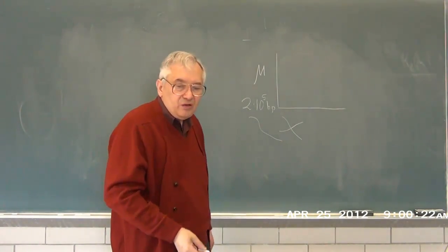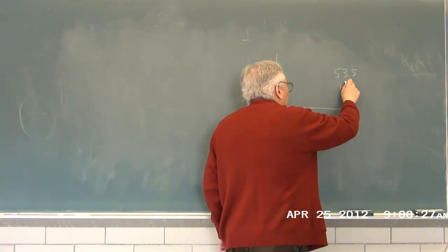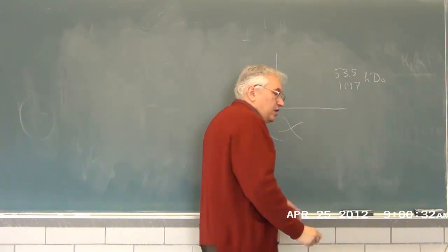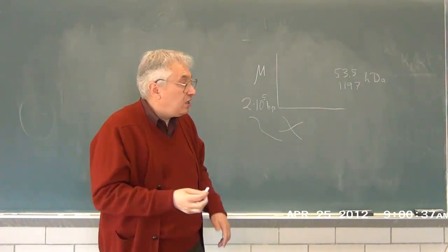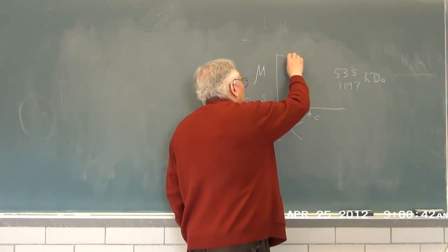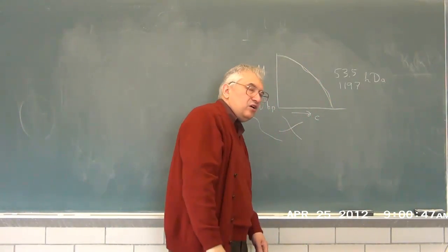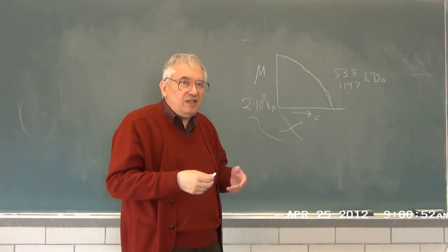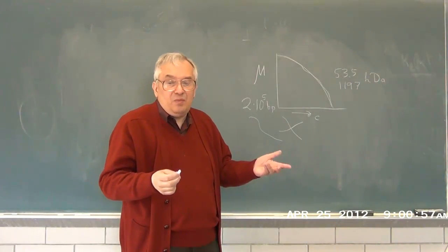And then you have a matrix polymer, which was either a 53.5 or an 1197 kilodalton polymer at various concentrations. So you then look at the mobility of the linear chain, the mobility of the star as a function of concentration. And what you discover is 2 lines are pretty much on top of each other. That is, if you look at electrophoretic mobility, linear chains and stars of the same, quite large size, move at the same speed, pretty much.